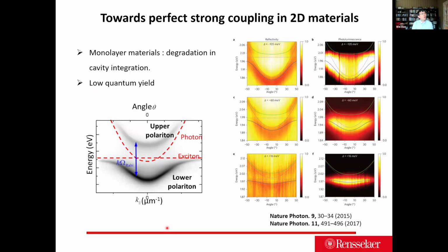Another system that people hope a lot for is to do this in two-dimensional materials, essentially the transition metal dichalcogenide monolayer. However, because the system is a monolayer, and we all know that if you fabricate a sample with certain things on top, you tend to introduce defects on the semiconductor, which makes the quantum yield degrade. Plus, in two-dimensional materials, if you have a big exciton binding energy, that means exciton annihilation is also promoted because your excitons tend to interact and generate phonons. So combine the two things as a drawback.